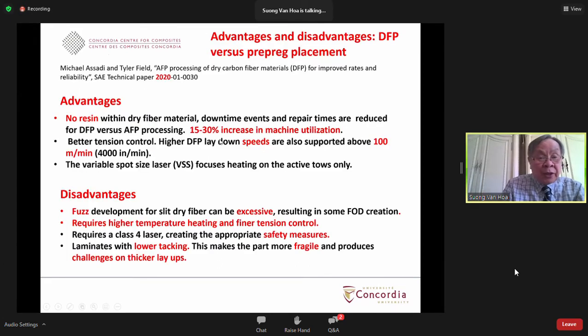So, the advantages and disadvantages of dry fiber. Because you don't have resin, the downtime, cleaning and repair times are less for DFP processing. People feel that they can increase machine utilization by 15 to 30%. Also the fiber has better tension control, and so the speed can be larger. And people usually use a laser to focus the heating on the active tow.